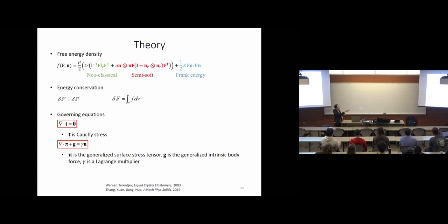Therefore, different from other typical polymers, the total free energy is a function of the deformation gradient, but also a function of the director. N is the director. It becomes a free variable which can change around, right? By minimizing the energy or using energy conservation, we can derive two governing equations, as we can expect, because now we have two variables. The first equation is still as usual, the stress balance of the Cauchy stress. But because we also have another variable, the director, we have a second governing equation which governs the evolution of the director. By the way, here we are not considering any viscoelastic effect, but right now we are further working on that.